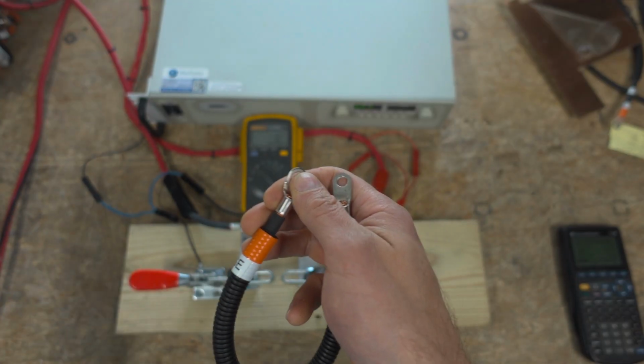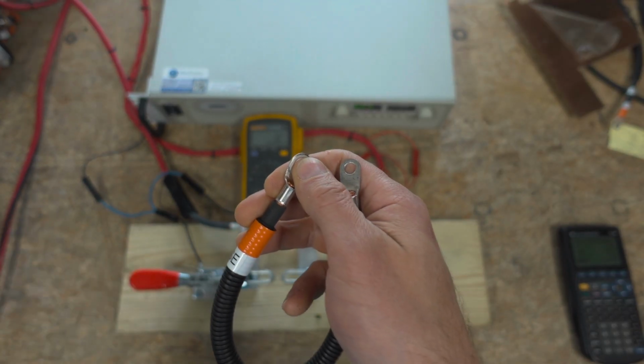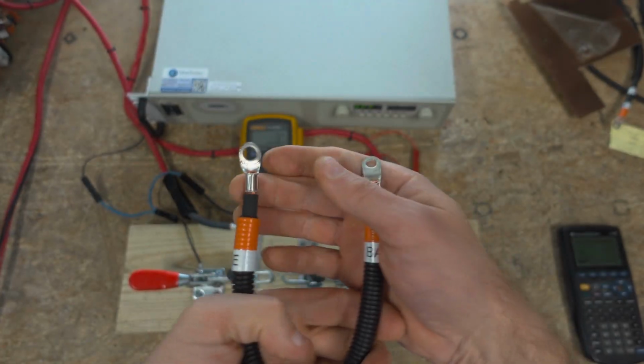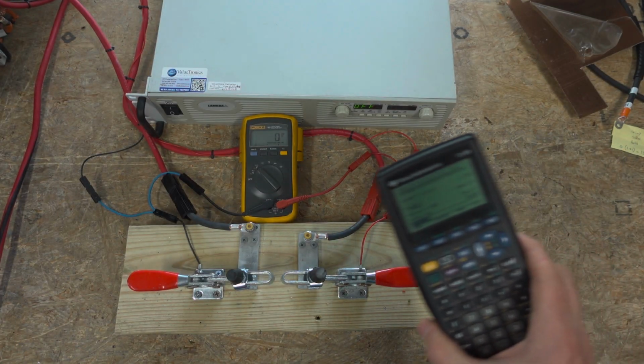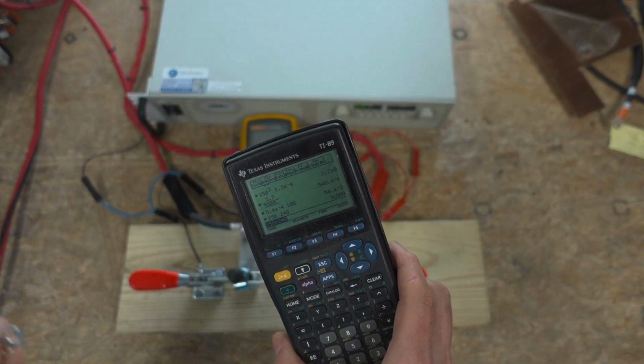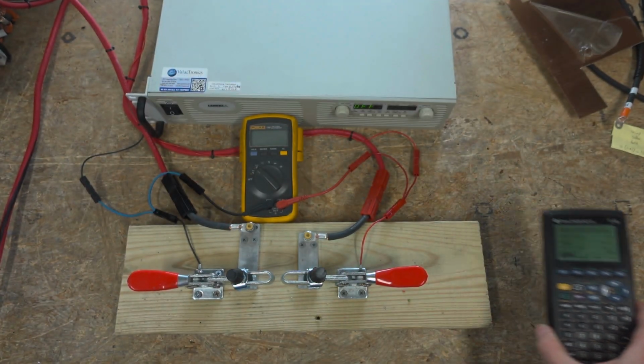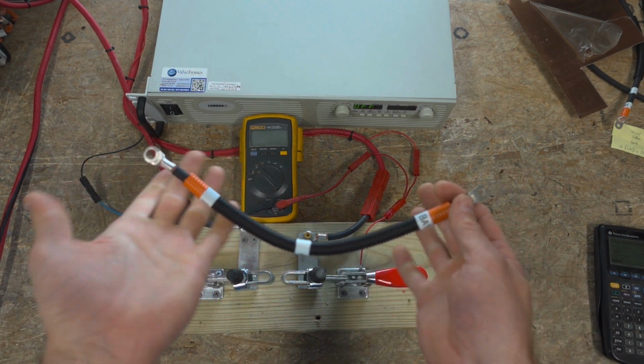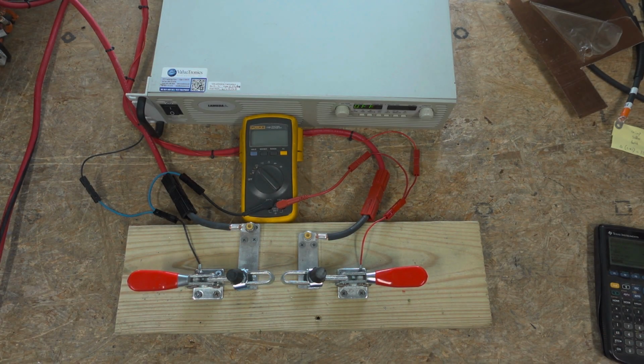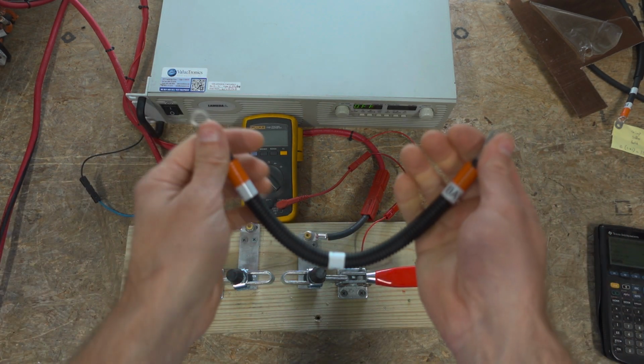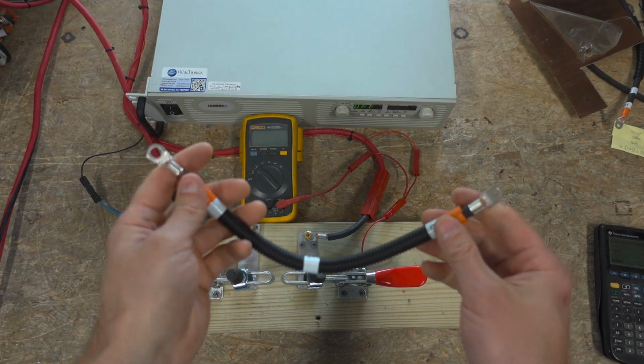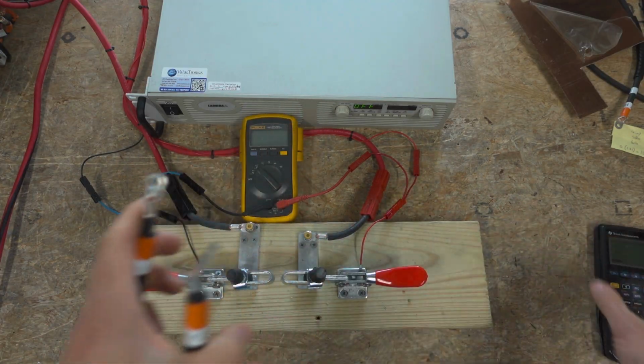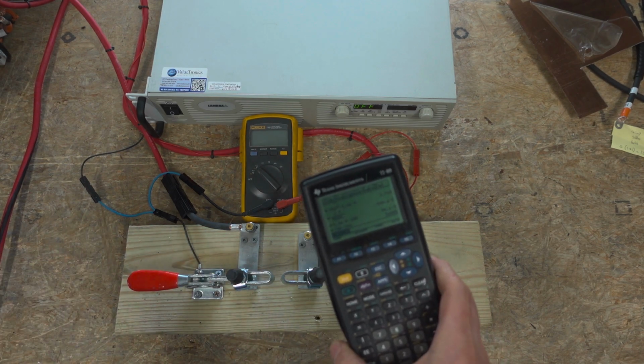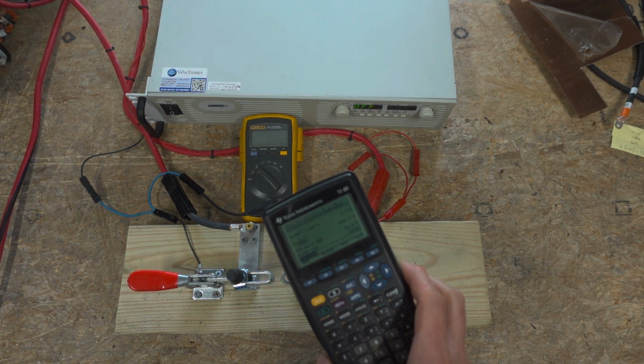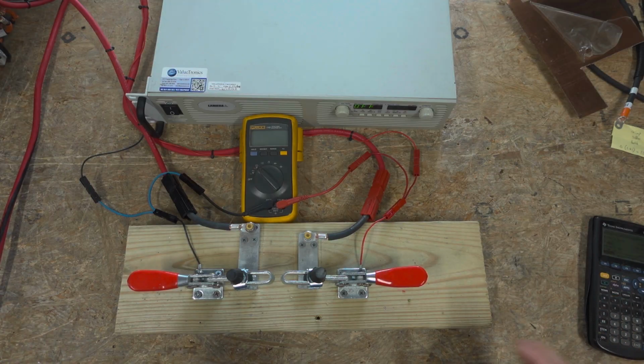One of my products has 10, one of them has 12. But you're talking overall, when you have 10 of these connections, you're talking about, in their test data, 30 watts of extra heat when you have a 5 kilowatt thing that it's connected to generating heat as well. So you're talking about less than 1% of the issue is here versus in the cell itself. So the point is, the claimed benefit of the slightly lower resistance, 120 microohms, is inconsequential compared to the other amount of energy inside of this pack that's being released.